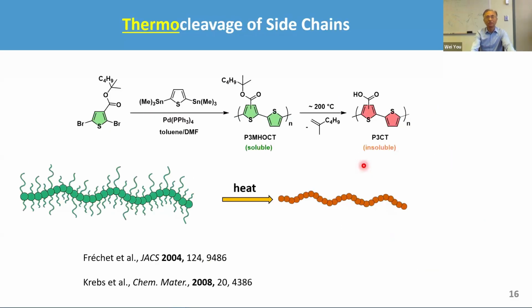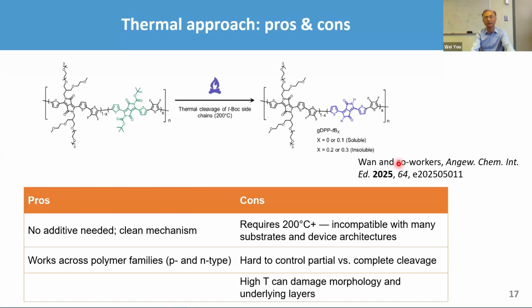Anyway, I want to talk about 3 general approaches people are using. One is called thermal cleavage. This is possibly most known to the audience here, done by Fréchet and Krebs 20 plus years ago now. What they do is take this tertiary ester, make the polymer, then heat up to about 200 degrees C, and you will be able to remove the alkene and it's gone, and you end up with a carboxylic acid. It becomes insoluble. This is the thermal approach.